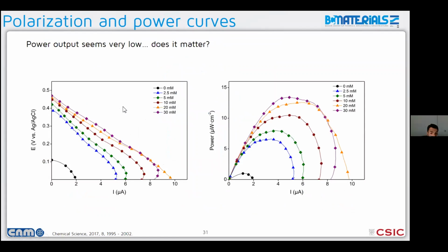So this was the system characterization, the polarization curves and the power curves. And as you can see, the open circuit potential was close to what we had estimated from the cyclic voltammograms, but the power was very little. So we were generating something like 10 to 15 microwatts per square centimeter.